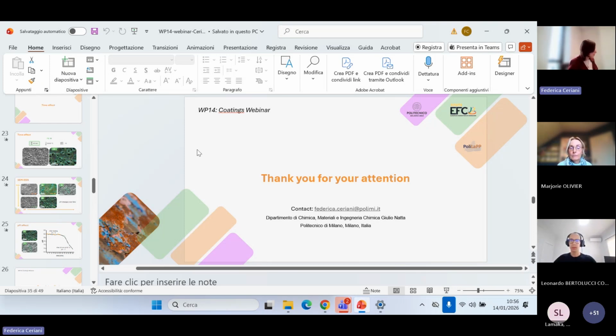It mainly depends on the fact that we want to reproduce what was already studied for aluminum, because my first experiments were performed on aluminum alloys coated with PEO, and I performed LDH sealing that is mainly based on the use of zinc nitrate. And let's say I'm curious to see if this type of sealing solution will be efficient also for the sealing of magnesium. Obviously, in this case, probably LDH structures are not obtained because, differently from the case of aluminum, there are not trivalent metallic ions. But anyway, it seems to work.